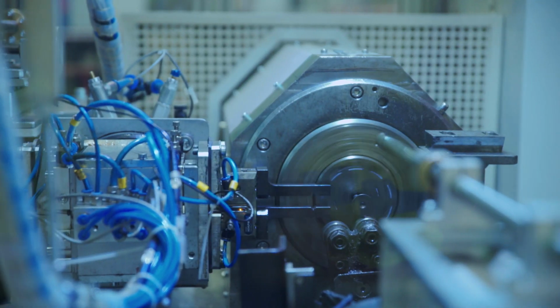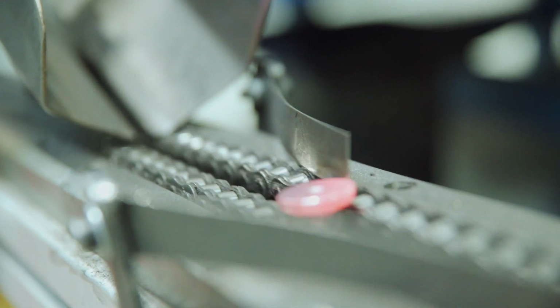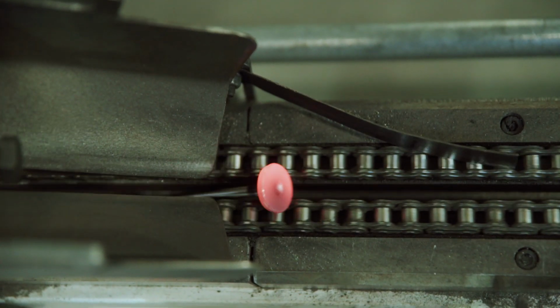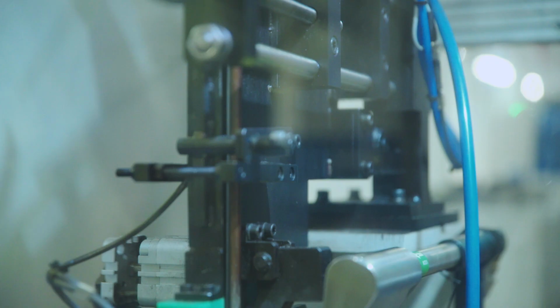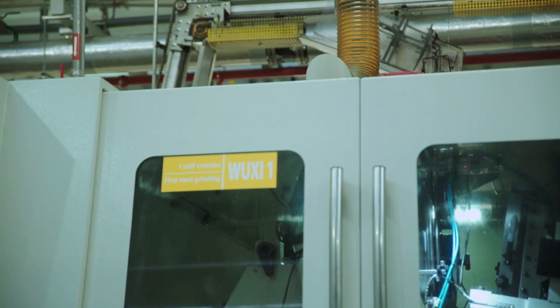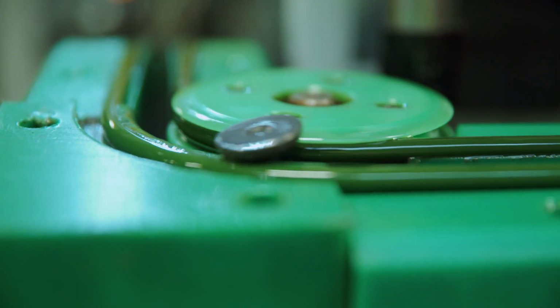To provide high temperature resistance inside an engine, the valve face is often made of stellite in a plasma seat welding process. The end of valve stem must withstand local forces and abrasion, therefore it receives an induction tip hardening process. The final dimensions and valve geometry are obtained in a grinding process. Chrome plating improves wear resistance.